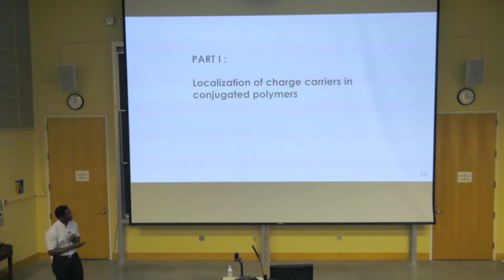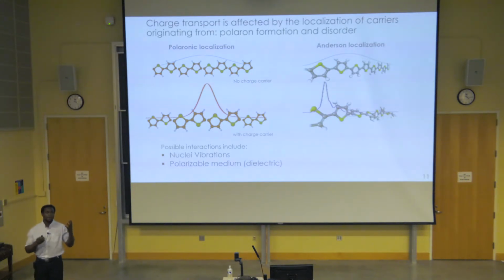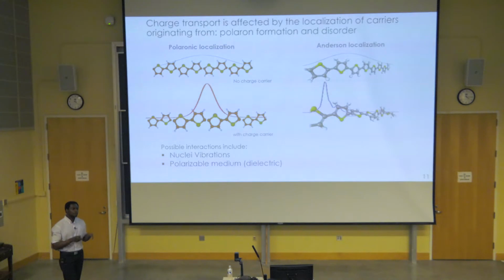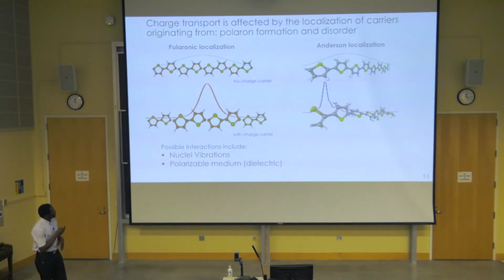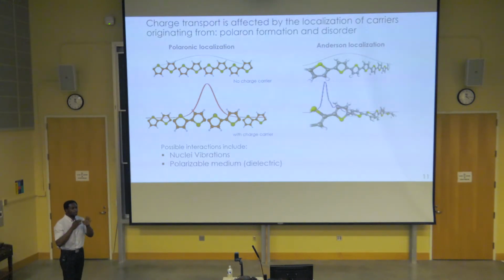For the localization of charge carriers, we have two different mechanisms by which charges within a polymer can localize. The first mechanism is through polaron formation. Let me just explain what this is. This is when a charge carrier is able to distort its surrounding medium, and the distortion in turn interacts with the charge carrier attractively, tending to localize it. Essentially what happens is the charge carrier redistributes itself spatially in such a way as to optimize the benefit of the attractive interaction with the distorted surrounding. And the second mechanism is through disorder, also known as Anderson localization.